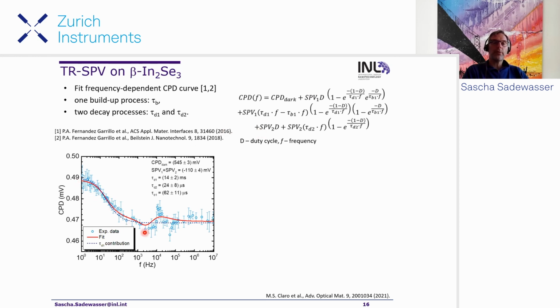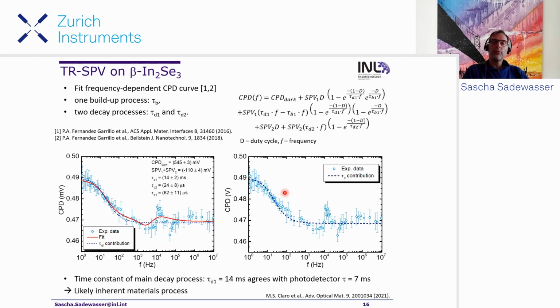And when we do this fit, we get actually a quite good match. And we get these three time constants, two in the microseconds and one in the millisecond range. So if we focus only on the process in the milliseconds, we can actually get a fairly good description of our data with a single process. And this time constant of 14 milliseconds is actually very close to the one of the photodetector. So if you consider that this was a slightly different substrate and possibly influenced slightly the material's quality, then we can fairly confidently say that the time constant of the pure material is probably the same as in the device. So it's likely an inherent material process that is determining the time response of the photodetector device.